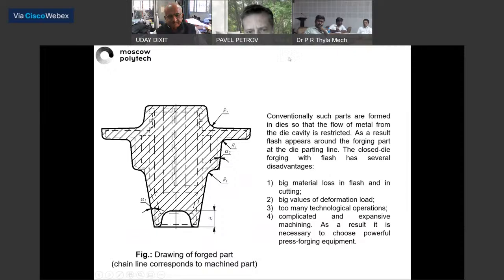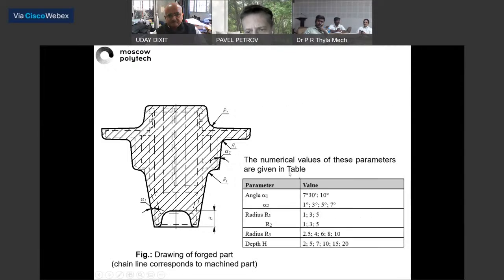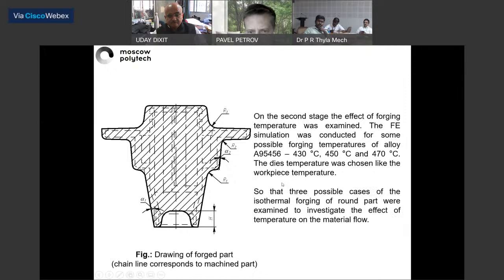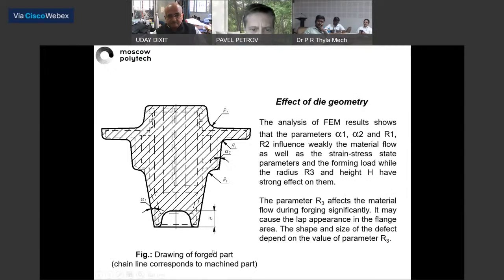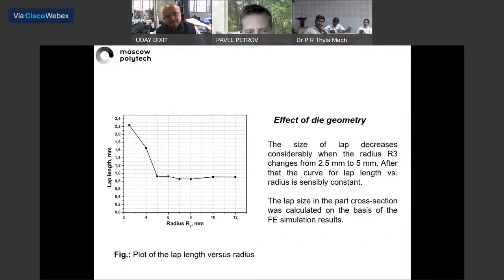For instance, some group of parameters connected to the geometry of the part. So 7 parameters were marked out. And as was investigated and resulted, a combination of the numerical values of these parameters could, for instance, reduce the lap length on the flange part of the forging, which was shown on the previous slide. The increase in radius allows to reduce the lap length twice.